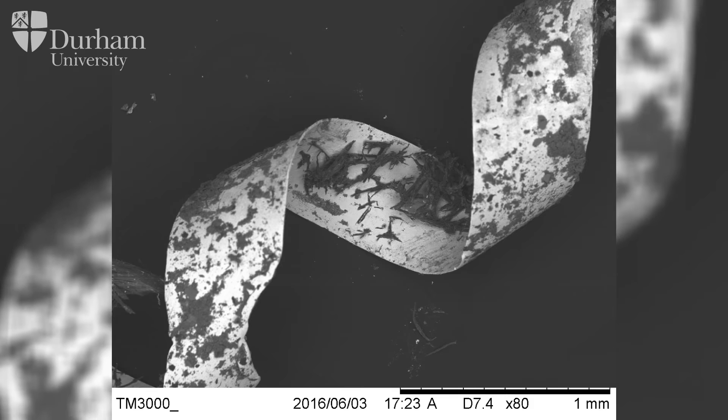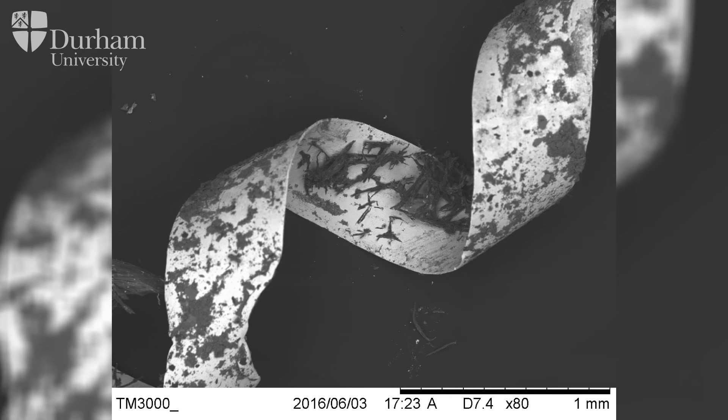What you're looking at is not an image in the way you're used to it — it's not a visible light spectrum. Our eyes can only see in the visible spectrum, and this response is at a wavelength much higher than our eyes can see, at a much higher energy. What you're actually looking at is a map of chemical density, translated so that your eyes can see it as an image. We wanted to understand exactly how these threads were made, their chemical composition, and their alloy composition, which also informs on age. We wanted to test exactly how pure the silver was, and we found these are made of an incredibly high purity silver — something approaching 95% to 99%. So pure it's difficult to detect what things were being mixed in with them, which in a normal situation for a ring you would definitely need to add something. But in this case, because it needs to be malleable and worked in a certain way, they could get away with using very high purity silver.